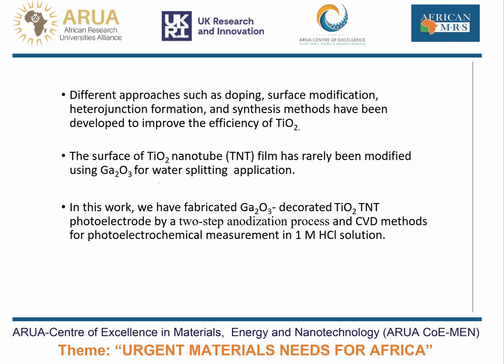The surface of titanium oxide nanotube films has rarely been decorated with gallium oxide nanoparticles. There are works that have reported its decoration with platinum, gold, silver, and so on, but research is really scarce on the decoration of titanium oxide nanotubes with gallium oxide. So in this work, we have fabricated a gallium oxide decorated titanium oxide nanotube photoelectrode by a two-step anodization process followed by a CVD method